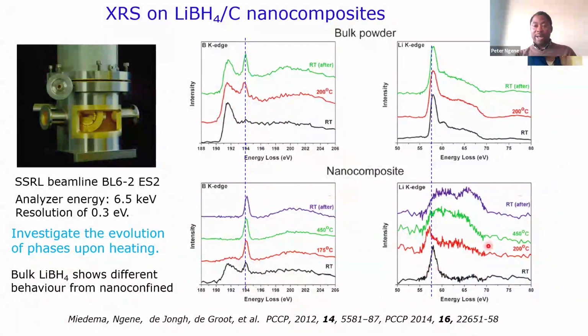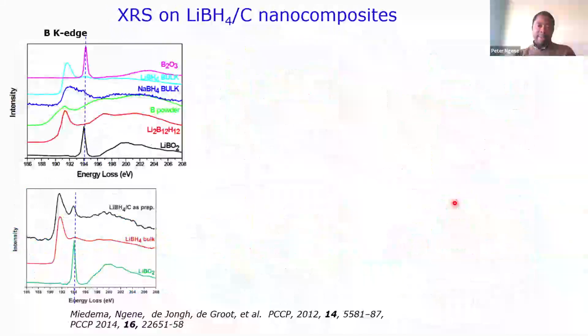If you look also at the boron, the lithium edge, I mean to say the lithium here, you see also the same thing happening here. So at room temperature, we have this, and then already when we heat our sample, you see that actually it changes completely. So of course, the signal to noise ratio was not good at that time. It has improved much better now, but at least it's good to show this data, also to show the journey we do in science, right?